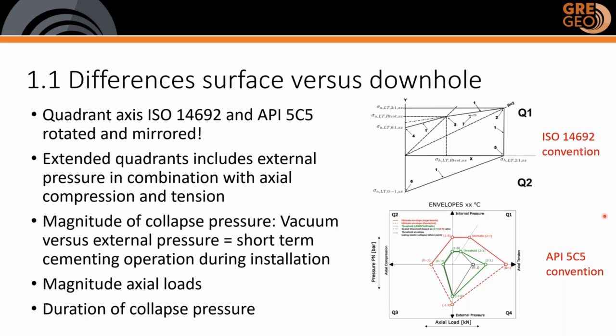ISO 14692 does not cover external pressure. Usually pipeline and piping systems are inherently resistant against vacuum conditions. So this was really a big challenge for this project. Also, there is a difference in the duration of loading. The most severe collapse condition is short term, and especially during cementing, during the installation phase of the project.